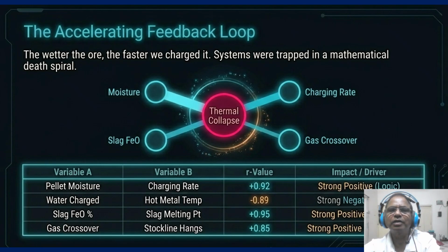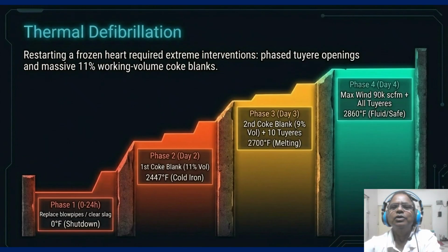So once the heart stopped, restarting it required a process we call thermal defibrillation. So thermal defibrillation, you don't just turn on a frozen furnace. So this slide shows the 4-day recovery sequence. Phase 1 was pure mechanical cleanup at 0 degrees. Phase 2 involved the first coke blank, a massive 11% working volume charge to get us to 2447 degrees.